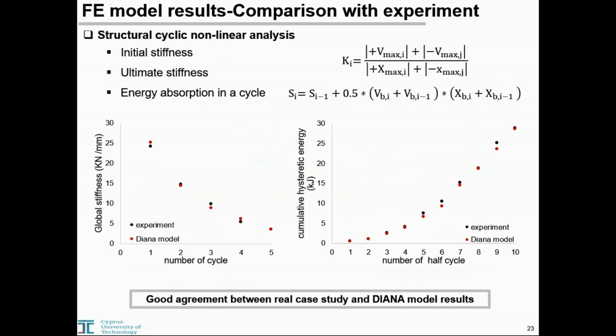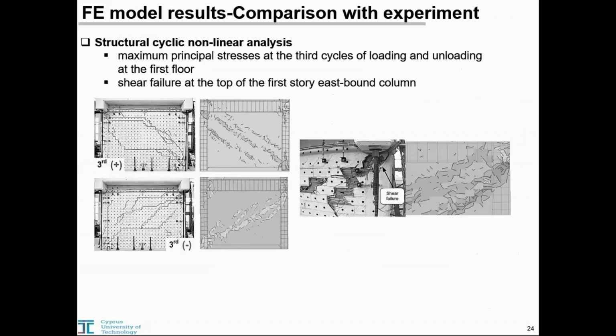This figure shows the comparison between experimental numerical results for Masonry-infilled frame in terms of global lateral stiffness and hysteretic energy, respectively. The secant stiffness degradation of the model is calculated according to these equations. In addition, for easy calculation, the evolution of the energy of the model is expressed by these expressions you can see here. From the figures, it is apparent that there is a good agreement between the numerical and experimental results for Masonry-infilled frame regarding the initial stiffness, ultimate stiffness, shear capacity, and energy in a cycle of loading and unloading.